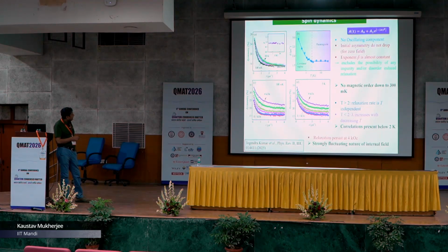This asymmetry versus time curve at different temperatures is shown. From this figure you can see that there is neither an oscillating component nor a drop in the initial asymmetry. The curve is fitted with a stretched exponential function of this form, and the exponent beta is found to be constant. So, it totally excludes the possibility of any impurity or disorder induced relaxation. Also, we see that there is no magnetic ordering down to 300 millikelvin because there is no oscillating component and no initial drop of asymmetry.